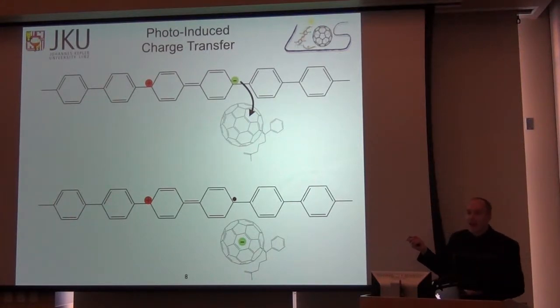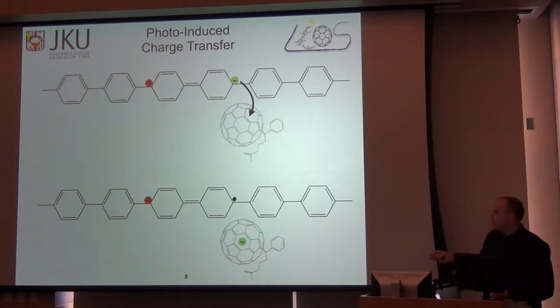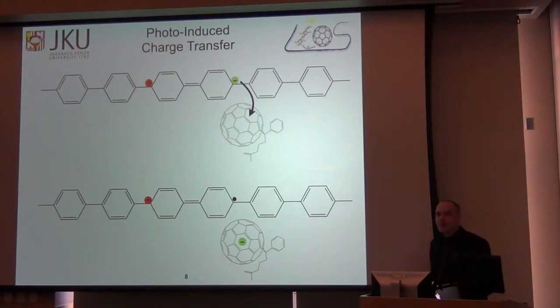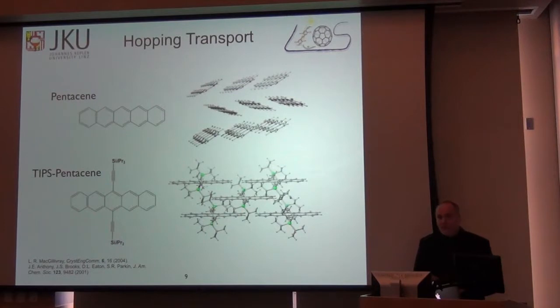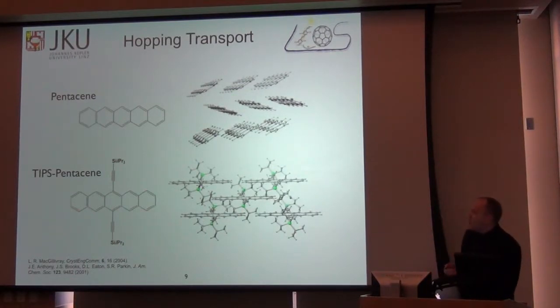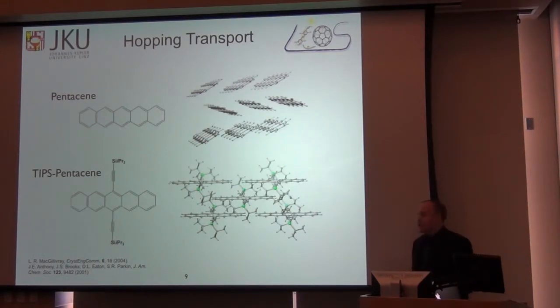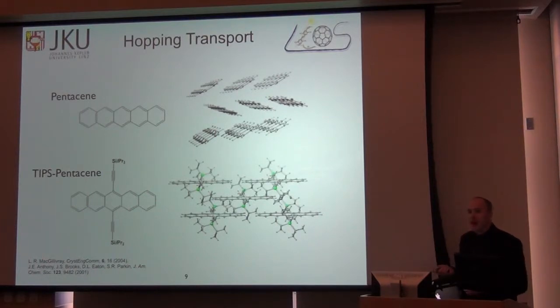These exciton states have a lifetime on the order of 100 picoseconds, but the charge-separated states have lifetimes on the order of microseconds. So this extra time that you buy at the cost of the energy gives you useful time to extract the carriers and make solar cells out of them. And once you have free carriers, whether they're photoexcited, or injected, or chemically doped, or electrochemically doped, the transport along the semiconductor molecule is limited by the molecular size. And so to get from one molecule to the other, you need other processes, and this is generally described as hopping transport.